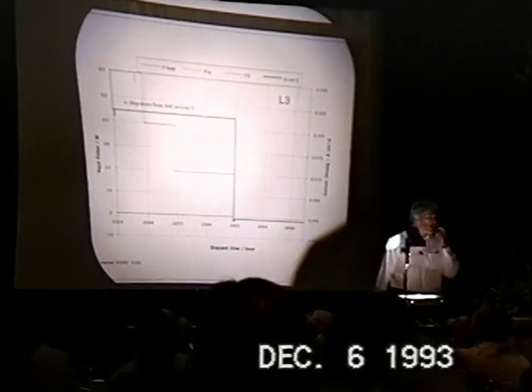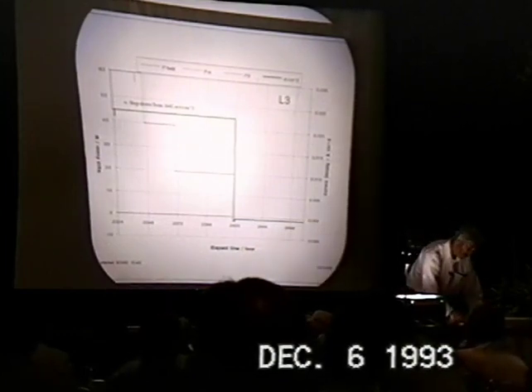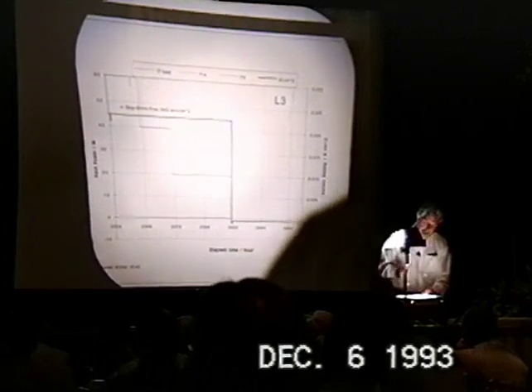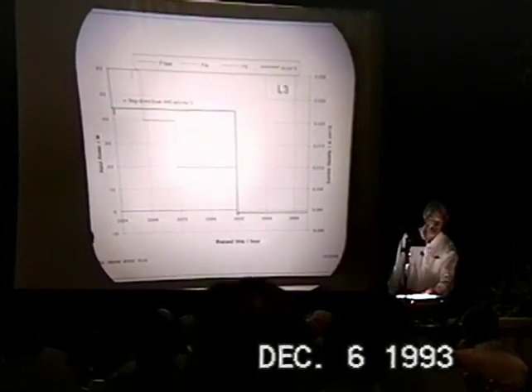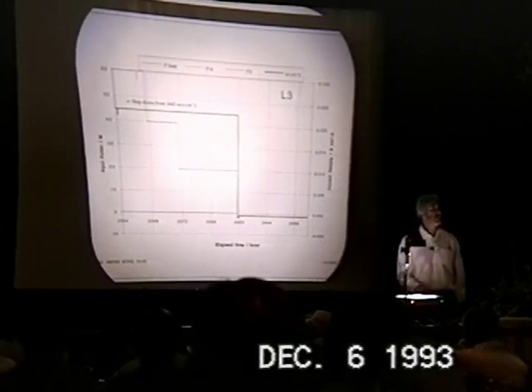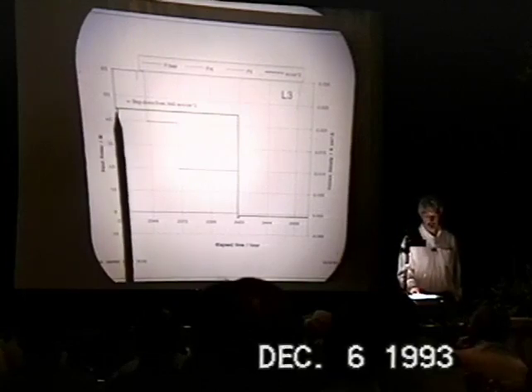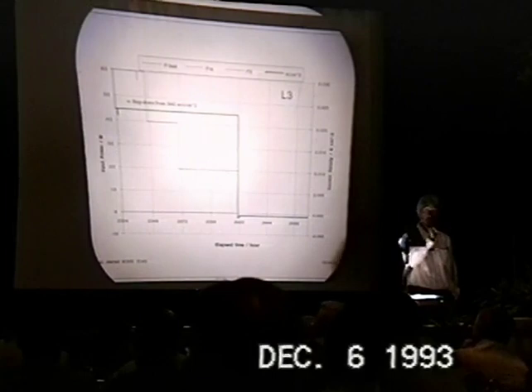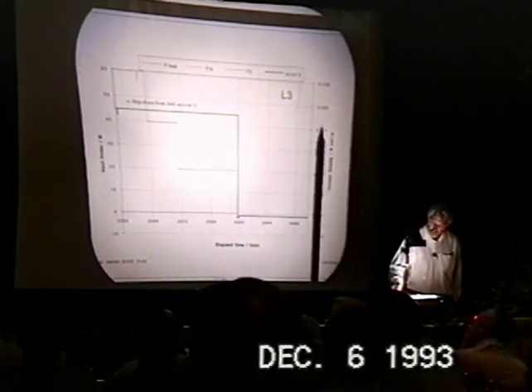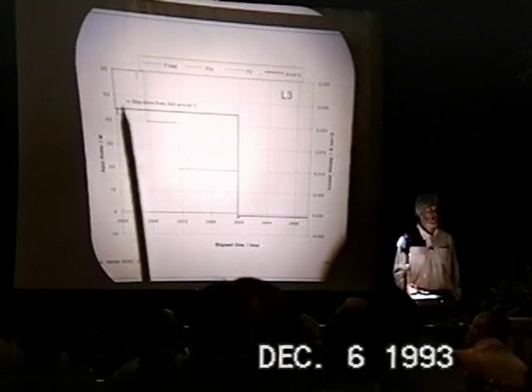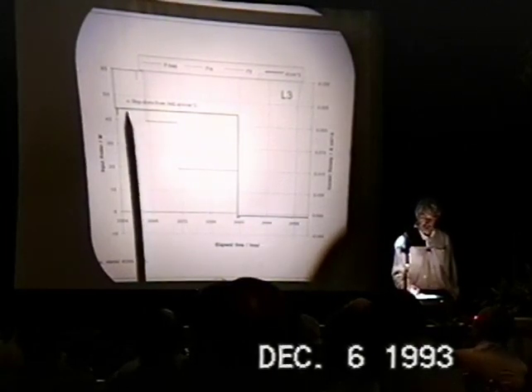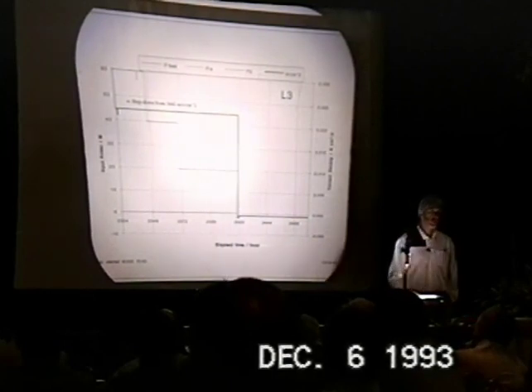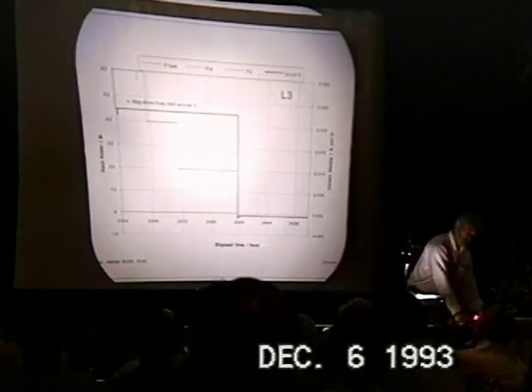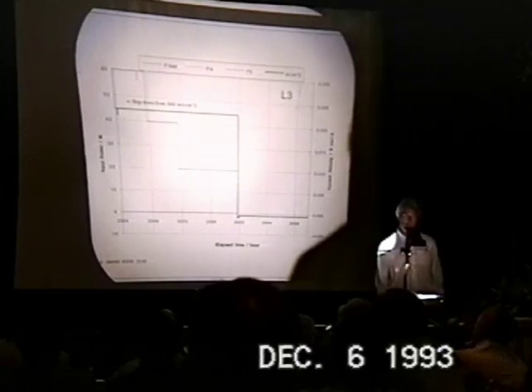Finally, heat after death. It's apropos to the question that was asked at the end of the last speaker. At the end of the experiment, current densities have been very large for a very long time. The loading has been maintained at a relatively high value for a significant period of time. At the end of the experiment, we stepped the current density down from 1600 milliamps per square centimeter to 23 milliamps per square centimeter to do our post-test calibrations. So this 23 milliamps per square centimeter is a small current density, below that value at which we would normally expect to see excess power.